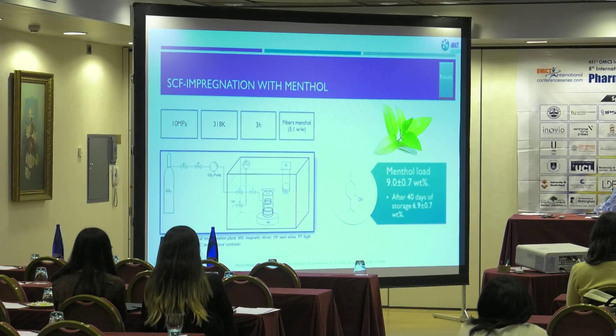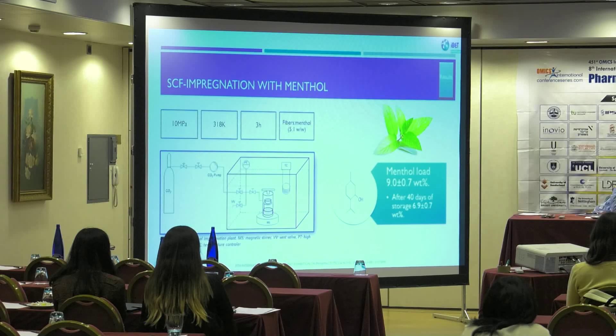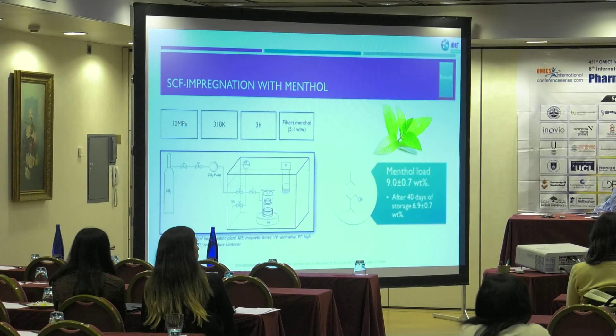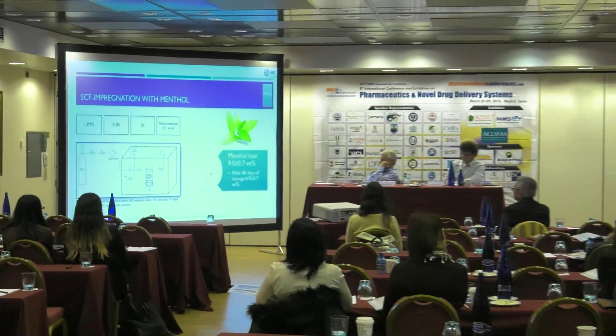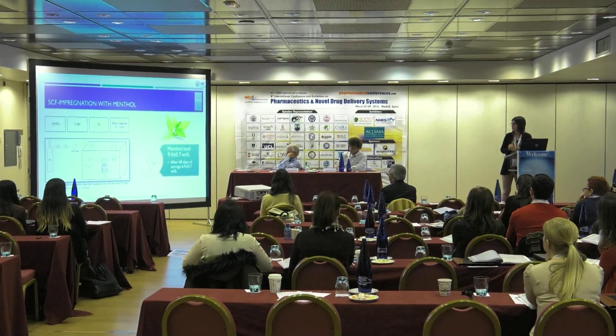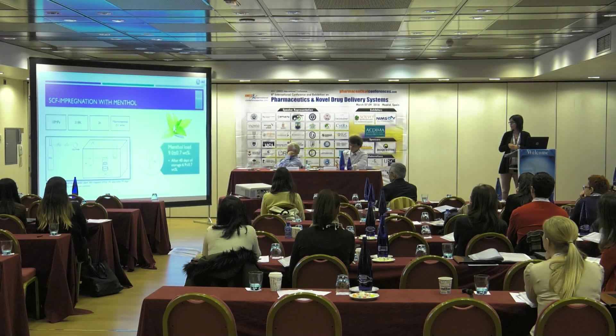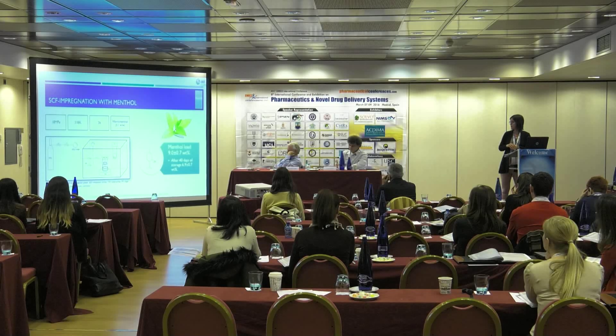We then loaded these fibers with menthol, using supercritical CO2 for the impregnation — it's a very simple process. You have a thermostatic high-pressure cell where you place the fibers and the menthol, you pressurize the system with supercritical CO2, the menthol is solubilized in the CO2 and diffuses into the fibers. The system equilibrates during three hours, and after that we got a loading of 9.0% weight total, which is above 50% encapsulation efficiency.